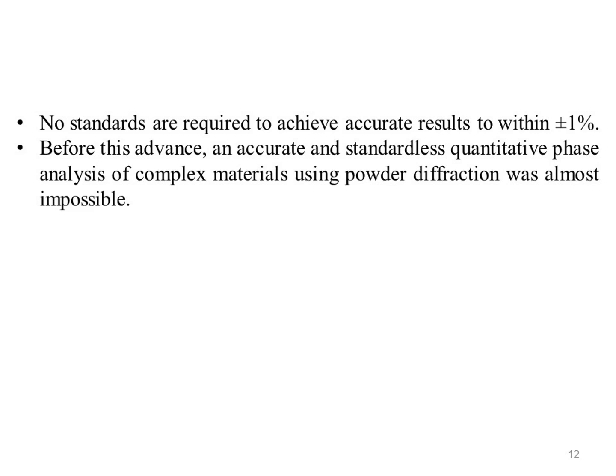The Rietveld method refines user-selected parameters to minimize the difference between an experimental pattern, observed data, and a model based on the hypothesized crystal structure and instrumental parameters, meaning the calculated pattern.